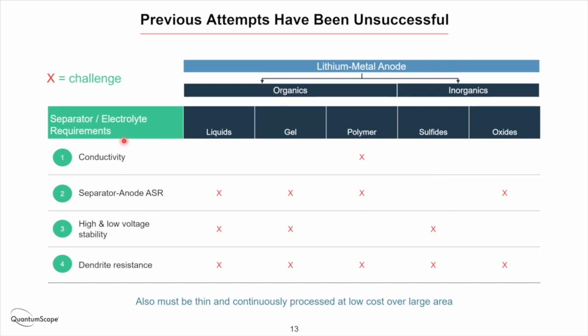So when it comes to the separator, some of the key requirements, at least in the automotive space, are it needs to have a high bulk conductivity competitive with liquid electrolytes. If you think about it, it's pretty impressive to have lithium hopping through a solid matrix as quickly as it'll transit through a liquid, but it is possible in some materials. Then the interface to the anode needs to be as conductive as possible. One of the things that's a little bit subtle and sometimes underappreciated is that there can be as much resistance at just the interface between the lithium metal anode and the separator as there is throughout the entire bulk of the separator. So to be able to have a high power battery and enable fast charge, you need to have a low interfacial resistance. ASR is area specific resistance.